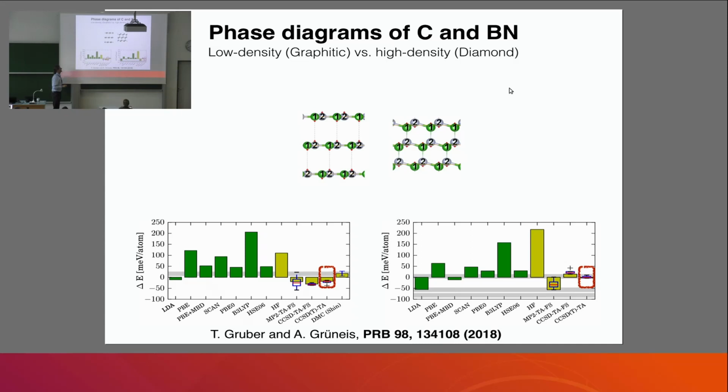These are quantum Monte Carlo results. They have achieved an almost perfect agreement with experiment, but there are also certain approximations involved. And I doubt that any theory is currently able to predict the real exact thermodynamic relative stability with plus or minus 10 to 20 millielectron volt errors, because there are also pseudopotential errors involved, et cetera, and this is not simply easy to address.